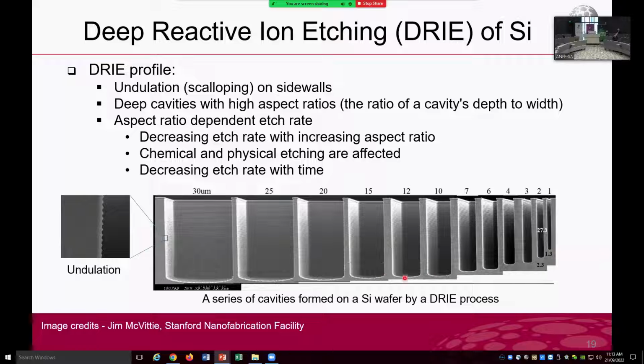Also, this SEM image highlights a phenomenon called aspect ratio dependent etch rate. As you can see here, cavities having wide openings have deeper cavities. That means that depending on the aspect ratio, etch rates are different. With high aspect ratios, the etch rate is lower. What's the reason? Chemical species and accelerated ions find it more difficult to reach the bottom of these narrow and deep cavities.